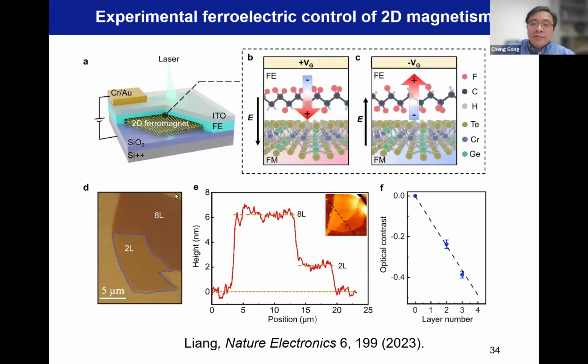So you can see figure B, later on I will revisit. When you polarize the ferroelectric in figure B and C, the interfacial atoms are different. In figure B, you have fluorine and hydrogen atoms directly bonding to the 2D magnet. But in figure C, only fluorine directly bonding to CGT. So that's what I said, polarization-dependent interfacial bonding or polarization-dependent interfacial crystal field. Then that of course will change all the magnet properties, including the magnetocrystalline anisotropy observed by coercivity change. So you can see this is an interfacial effect, should be more prominent for 2D rather than 3D samples.